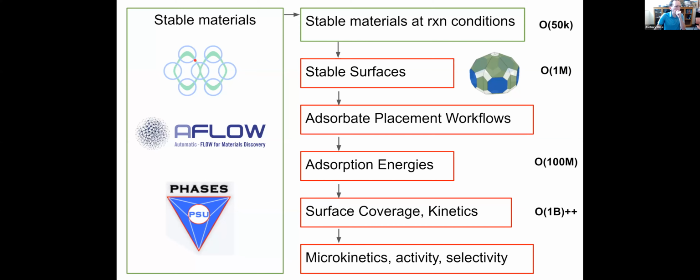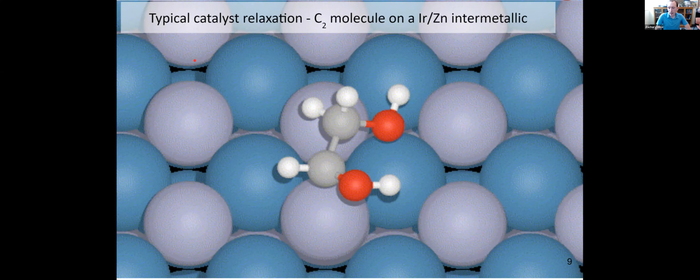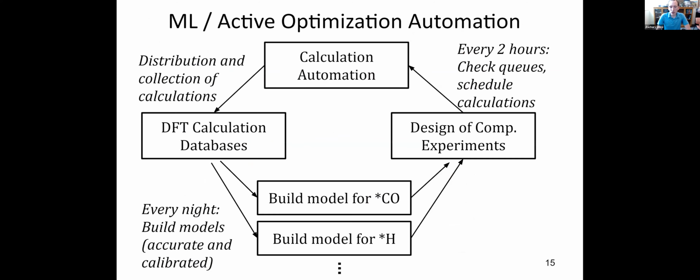Okay. Sorry. So on slide 15, the question is, I mentioned ML-based models. In this case, they were not interatomic potentials. So what was going on was I would show it a site, like CO sitting on top of a nickel, and I would ask the model to directly just tell me the energy. This is the energy is what I care about. That's the GCO I was showing before. The more general thing is build a machine learning potential and actually do a relaxation and say, what is the best site on a surface? But when we did this work 4 years ago, it was impossible to build a machine learning potential that worked for CO across any arbitrary metal surface.